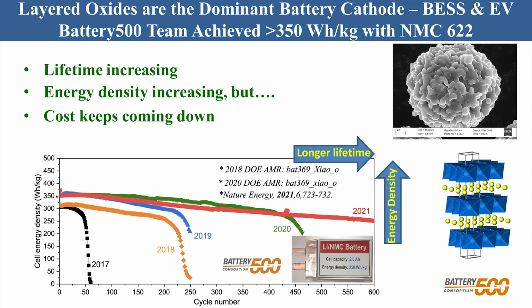These use pure lithium metal anodes. They used ether-based electrolytes, because ether-based electrolytes plate out lithium better. Essentially the same electrolytes at that time as we used back at Exxon, but now much improved. A year later, we got over 200, and a year after that, we increased the energy density up to 350, and I think as of the present time, we've got about 800 cycles out of these materials, and this is